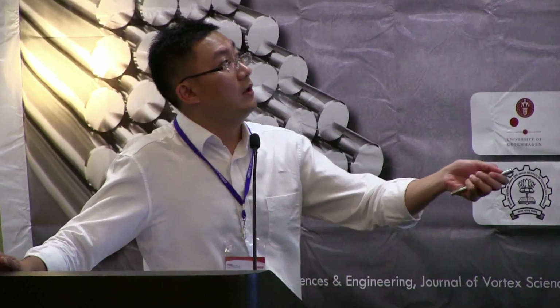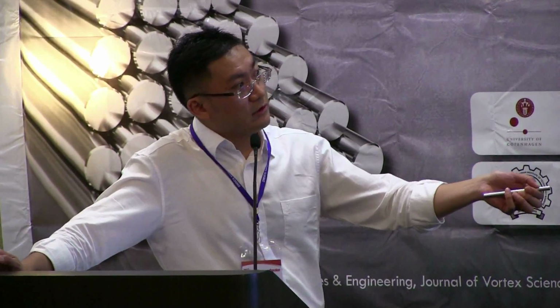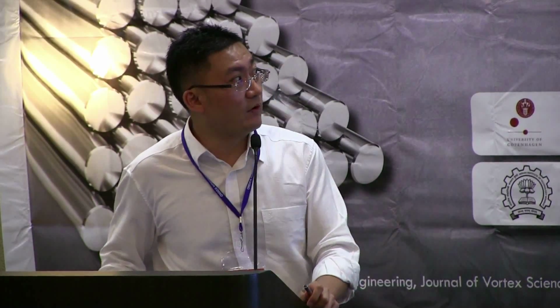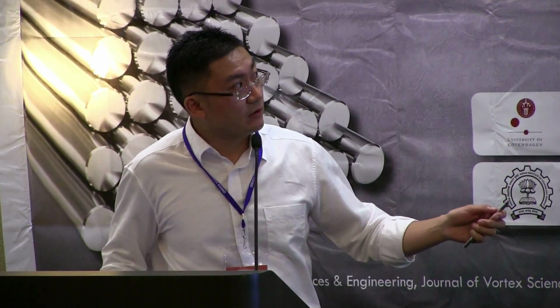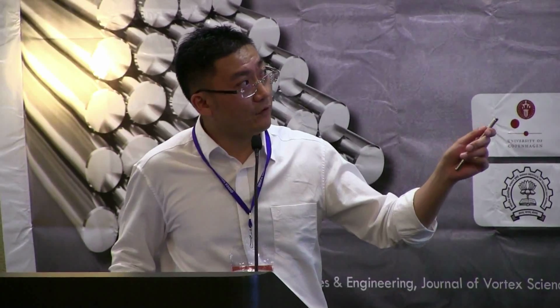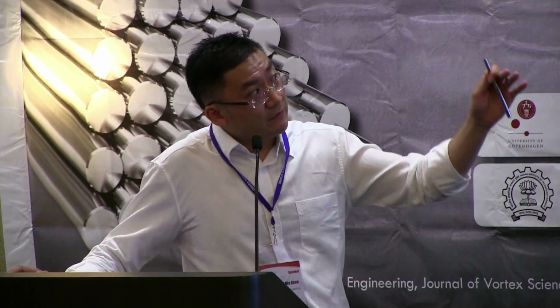Okay. So we will look at the stability. Usually we have a cycling number. You can see from 0 to 1,500 is a decent cycling to evaluate the performance. In the previous study, the performance was recorded at 30, because after 30 to 150, the cyclic voltammogram is similar, not much change, so that is already stable.